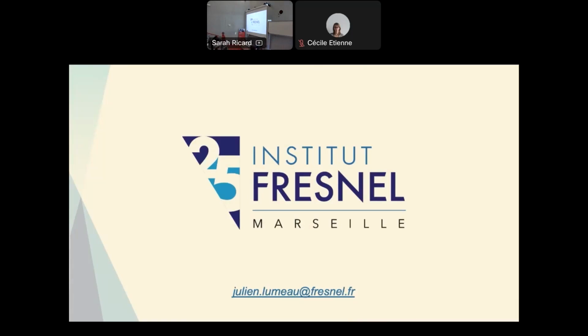Right, for these colors, we change it from tens of nanometers to hundreds of nanometers. It's between, let's say, 20 and 500 nanometers. Then after, depending on the thickness, also it will affect the angular sensitivity, because if you make it thicker, your interference fringes will be sharper, and therefore you are more angular sensitive.